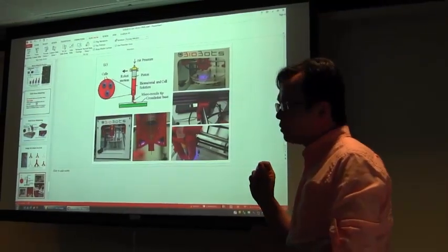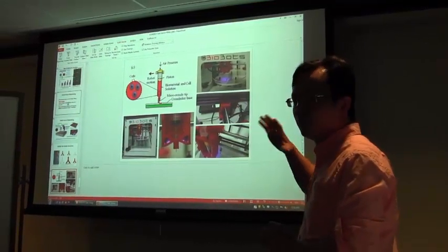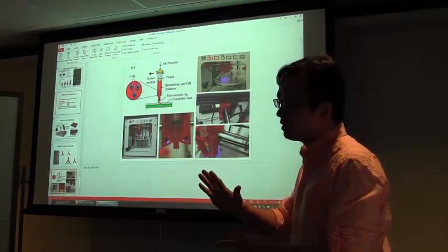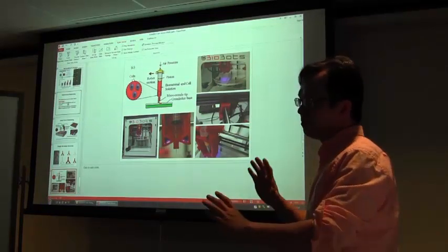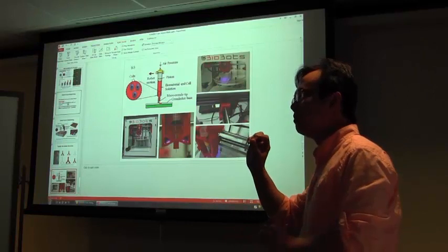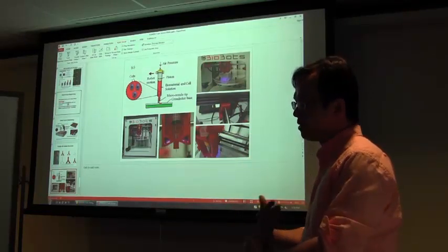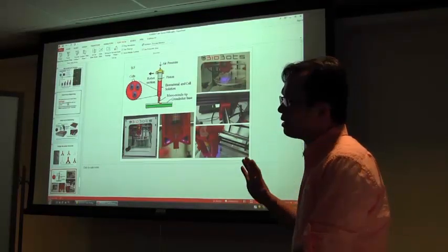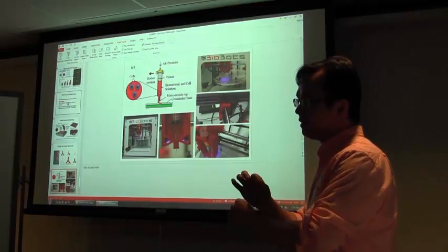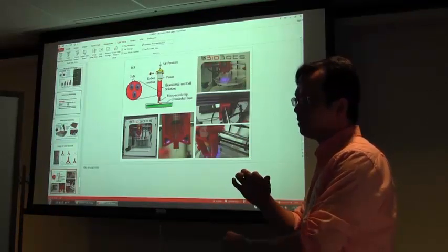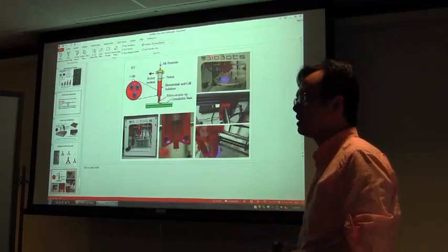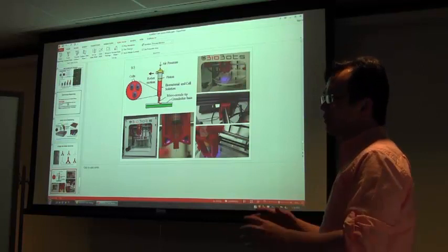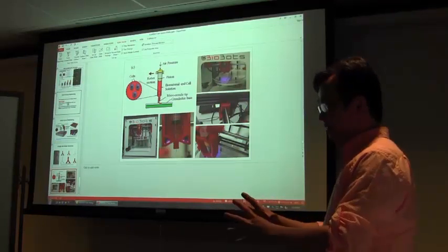So one thing, it depends on the needle size, right? Another thing, it depends on the method you push the polymer. If you use the hand, you cannot control really well. If you use the air pressure, even if you have a bigger needle, you can still produce a smaller stream, based on the pressure. So that's why the machine uses air pressure to push the material. It can even adjust the size of the beam from the same needle. That's one of the good things in the technology. So yes, you're right. Using different sizes of needle is one way to control the resolution.